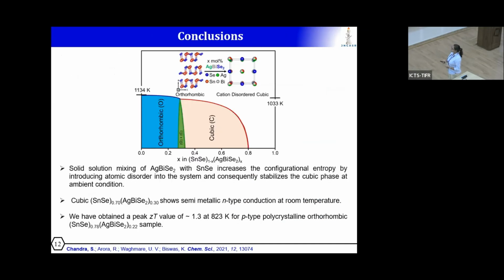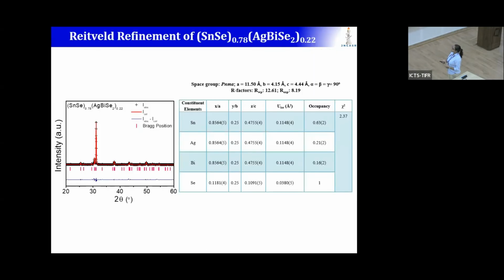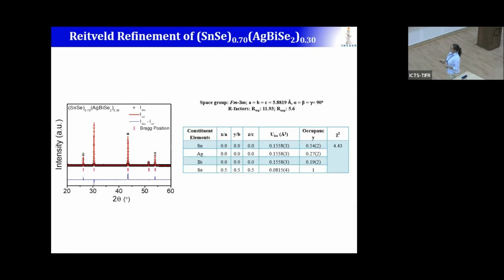Yes, I have not shown it here, but I have done the Rietveld refinement for this 22 mole% AgBiSe2 alloyed sample. The silver and bismuth are going to the tin position, and I have done it for the cubic sample also, where we can see that they are going to the cationic tin position.